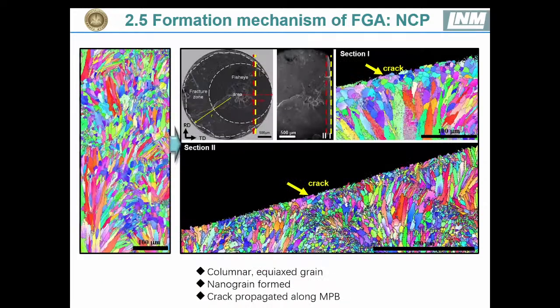And here in our analysis, also for this additive manufacturing analysis, we can observe some nanograin size at this crack tip and within the fish eye, within this FGA area, as we show here in our analysis. And we can also see that the crack initiated and mainly propagated along this melting pool boundary, and finally goes to failure.